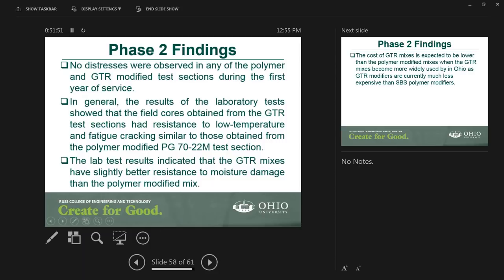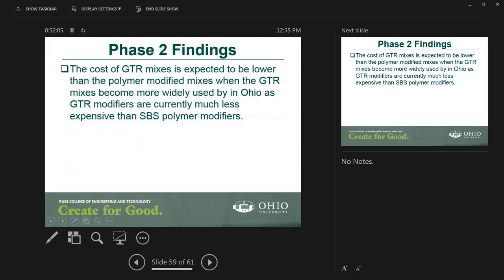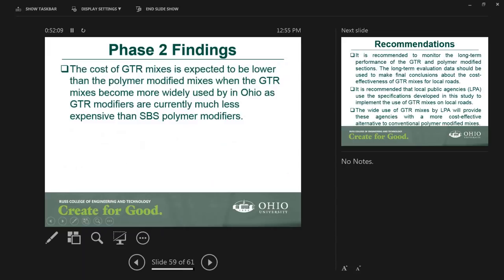We have seen that in certain cases it has actually better resistance to moisture damage. But again, the differences are really small, so we cannot say that it is statistically significant. Now, in terms of the cost, the initial cost of the GTR mix was higher because it was a pilot study. But based on the analysis that we have done, there is a potential that GTR asphalt mixtures, if they are widely used in Ohio, will be less expensive than the SBS polymer modified binders.